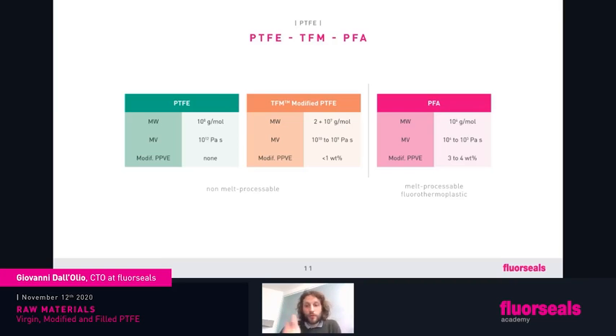When we add the modification, we're talking about the orange column, modified PTFE, we add a very small percentage of modifier, less than 1%. This will lead to a lower molecular weight and to a lower melt viscosity. So still modified PTFE is not melt processable, but we are going down. So we are getting nearer to the melt processable polymers.